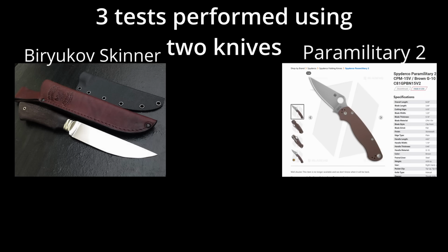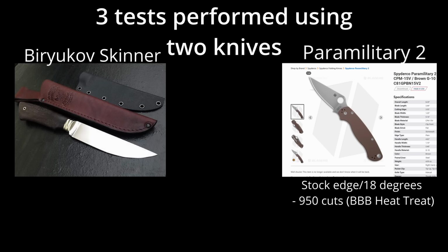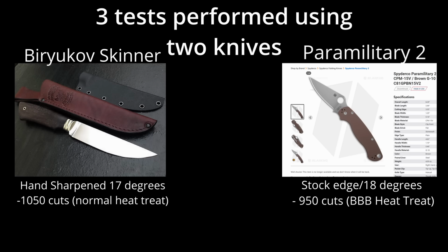The stock Paramilitary 2 with a belt ground factory edge at 18 degrees per side resulted in an impressive 950 cuts. This might not seem like a strong argument when compared against the traditionally heat-treated Biryukov Skinner with a 17-degree hand-sharpened and polished edge that achieved 1,050 cuts.